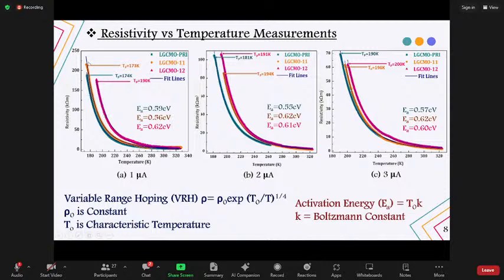And the overall value of the resistance is found to decrease with respect to applied temperature. That is because at the higher temperature range, the charge carriers gain thermal energy, and that can effectively contribute to the conduction process. This experimental data can also be understood in terms of the theoretical measurement.